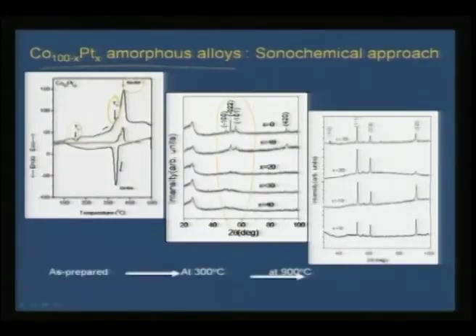So we can make powder compacts of this cobalt platinum and anneal it at 300 to do electrical resistivity measurements, and this figure shows the XRD: for 0% platinum you see a small signature of HCP, and as you increase the platinum content you see an almost amorphous pattern for the as-prepared compounds. But when you heat it at 900 degrees C, in the case of both the cobalt nanoparticle as well as the 30% platinum nanoparticle, you do not see the HCP which is supposed to be the case, whereas you see a complete FCC transformation. That is the beauty of the sonochemical reaction, because FCC is not possible to stabilize below 1000 degrees for cobalt platinum alloys.